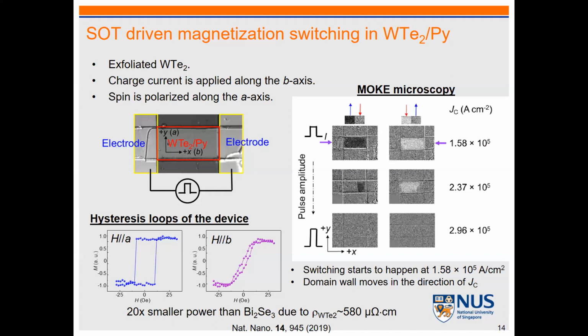Initially, of course, we started with the Scotch tape, the so-called Nobel Prize technique. You do exfoliation, then you find the right thickness, then you can deposit permalloy on top, and we can do the same thing. We apply charge current, black to white domain, white to black domain. You can do this kind of thing with much smaller charge current density.